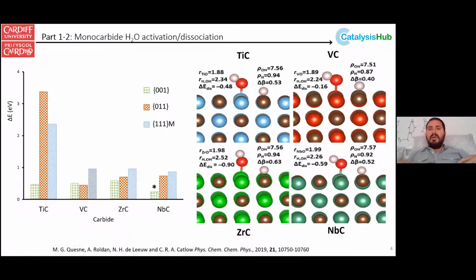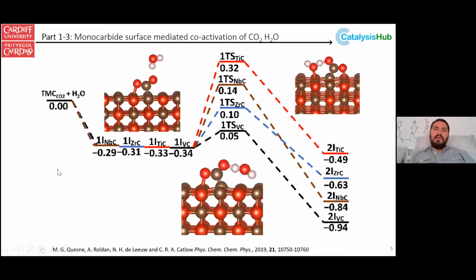So then we thought, okay, what happens when we co-bind CO2 and water, which is what you find in the flue gas? So when we looked at this, we decided that this scheme has everything set to 0 with the CO2 bound on the surface. There's a slight difference per surface, but we were really looking at what the effect of the added water absorption would be on the overall exothermicity. We find that the reactant state, which consists of the CO2 that's bound plus a hydrogen bond to the water through one of the hydrogens, is about the same, which makes sense because it's about the energy of one hydrogen bond.